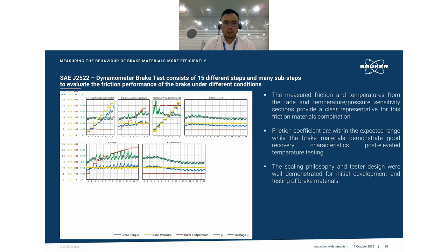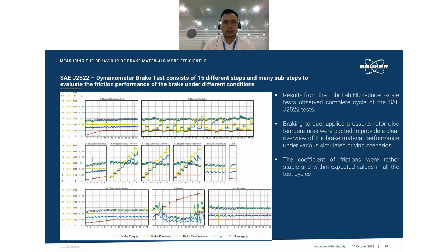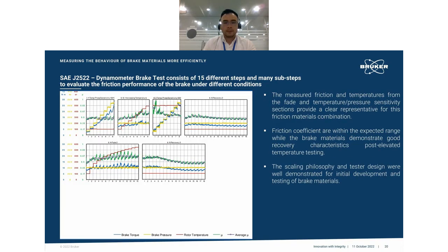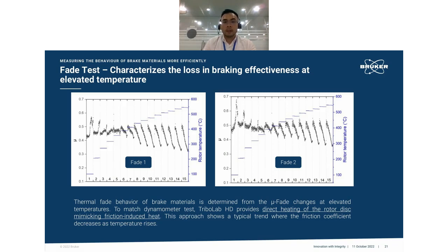So, for instance, between these two slides, there's this fade one in 6.9 that's on the third row of this image. And also on the second row, on the second image, is the fade two. So if these two graphs are of interest, we extract the graphs out and we're trying to compare how the brake effectiveness is being affected at elevated temperature, from 100 degrees Celsius going up all the way to 550 degrees Celsius. So having this type of side-by-side comparison of this one type of brake pads between fade one and fade two, an initial deduction or conclusion that we can make is we can actually determine the thermal fade behavior of brake